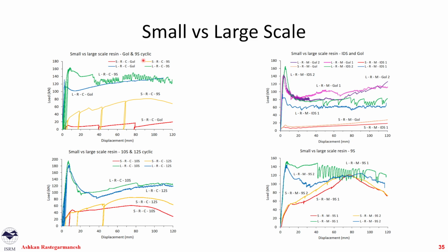The other one, these are the graphs for cyclic for different cables. As you can see, the cycles in the larger scale are mostly in the first 10 millimeter, but in the smaller scale, they are spread apart. And the load values, again, our smaller scales are lower, between around 50 to sometimes 60, 70% lower, or sometimes they tend to be much closer. So again, it's very difficult to say that with twice the embedment we get twice the load, because of the change of the confinement and the loading.